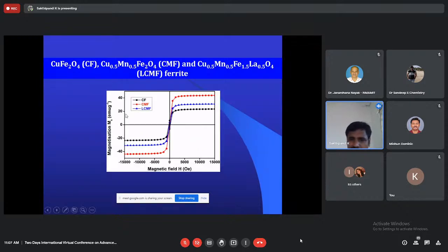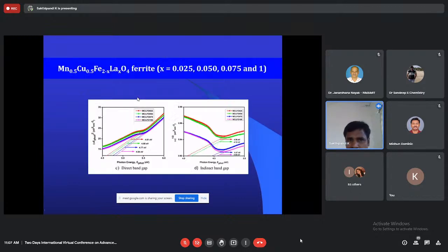So the magnetic field also decreased. For this element, the magnetic field is a little increased. However, for the dielectric constant, I have compromised with the magnetic properties. In the same way, I used different ratios of the lanthanide with this. The band gap is a little bit increased, but band gap is not a parameter for microwave absorption. However, a higher dielectric constant is needed for the materials.